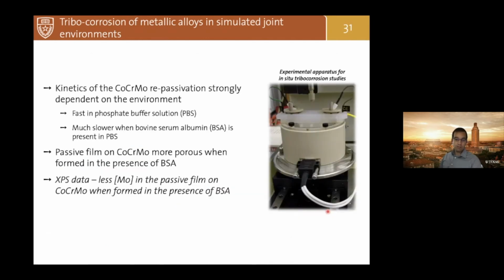So these are preliminary results that we have. We look at state-of-the-art material, cobalt, chromium, molybdenum, and in particular in this set of experiments we look at how this material repassivates in the presence of an environment that contains or does not contain the bovine serum albumin that is present in our synovial fluid. So we coupled electrochemical experiments and measurements with sliding experiments.